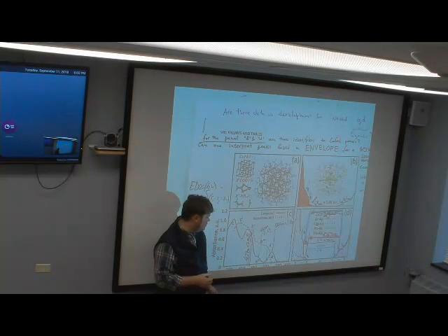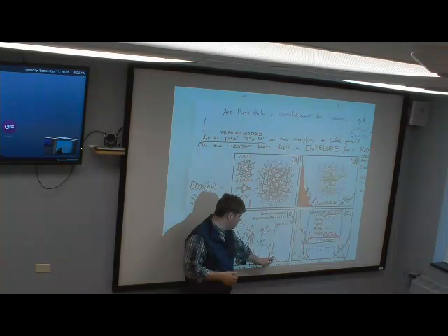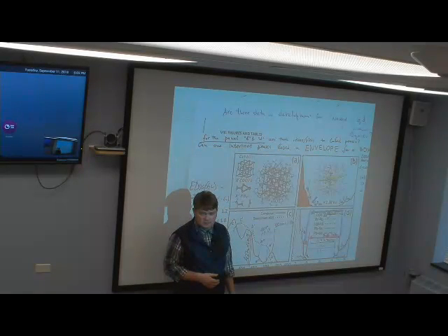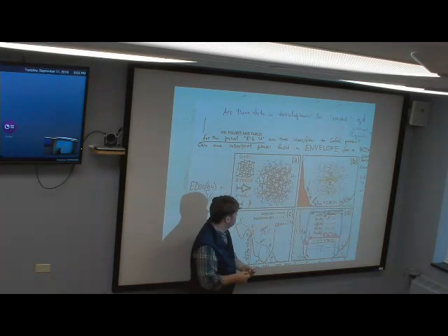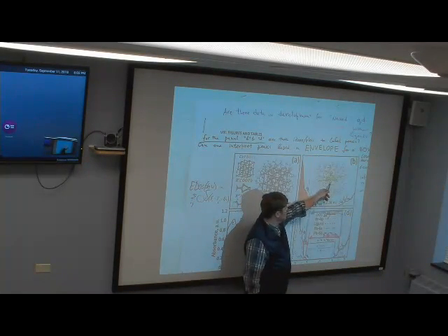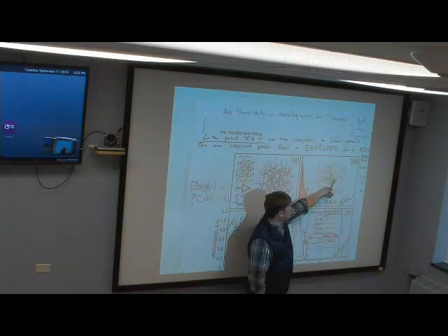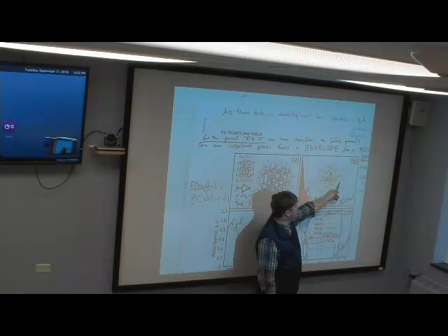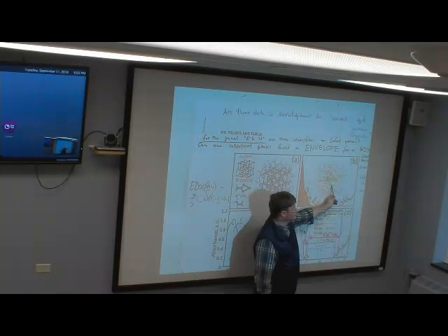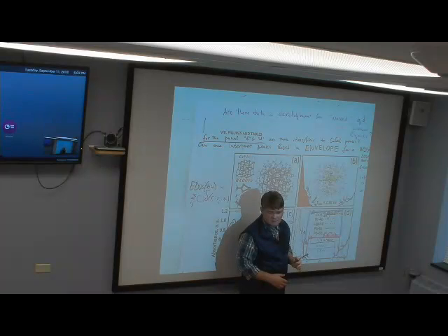I wouldn't agree that feature A without prime compute is an artifact. It looks, at least from what I see and what Aaron is explaining, as very reliable. The HOMO orbital looks as it is expected. So it's localized on bromines, and it is only those bromines that are not on the surface but in the center, in the core of this structure.